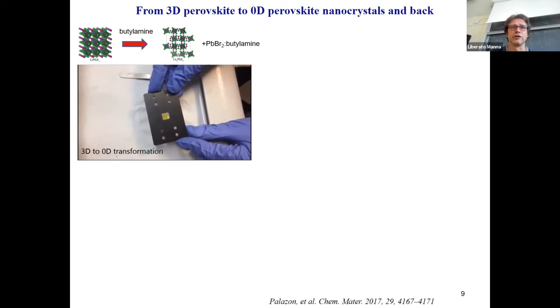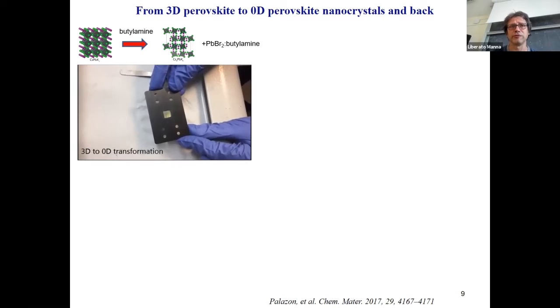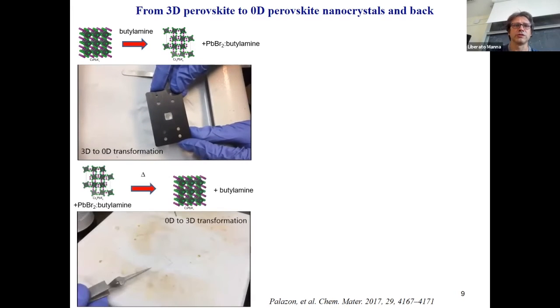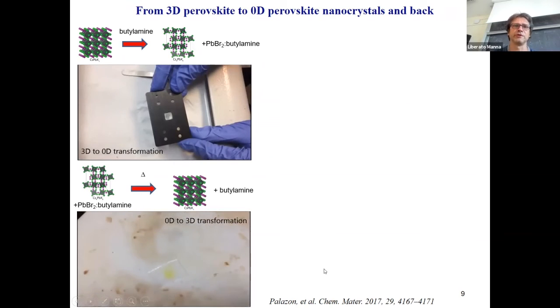So this is a film exposed to vapors of butylamine. Butylamine extracts lead bromide, and you form a 0D phase, which is an insulator. And you can do the same reaction back by heating up this film. So butylamine is released into the atmosphere, and you get a reinsertion of lead bromide into the perovskite phase.